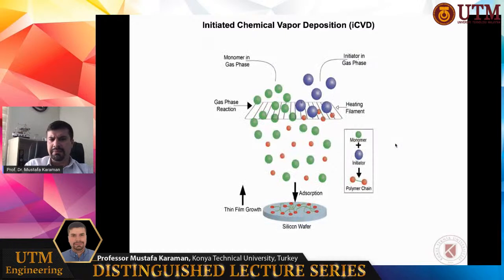Here you can see the mechanism in more detail. We feed two types of precursors, monomer and initiator. It's quite like the usual bulk phase polymerization system. But here, everything is carried out in the vapor phase, under vacuum. Here you can see that the monomer molecules pass through the filament array and adsorb physically on the substrate surface. Here the substrate is a silicon wafer. The monomer molecules are not affected by the temperature here because the temperature is not high enough to dissociate the monomer. It is just enough to dissociate the initiator molecules.